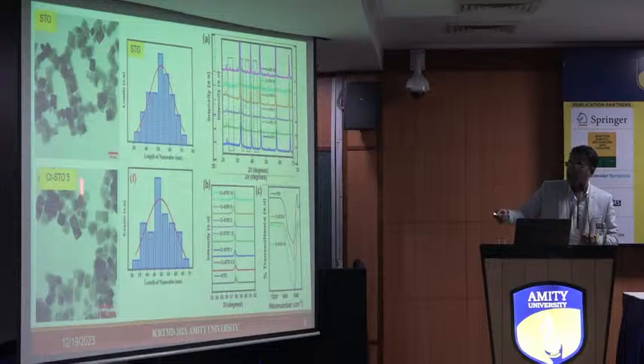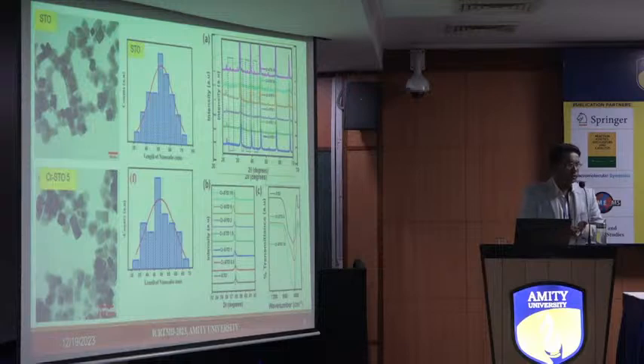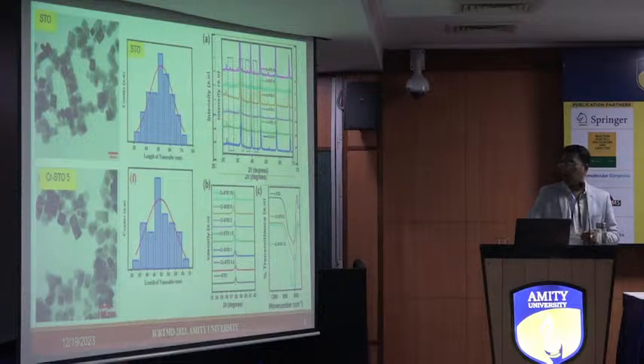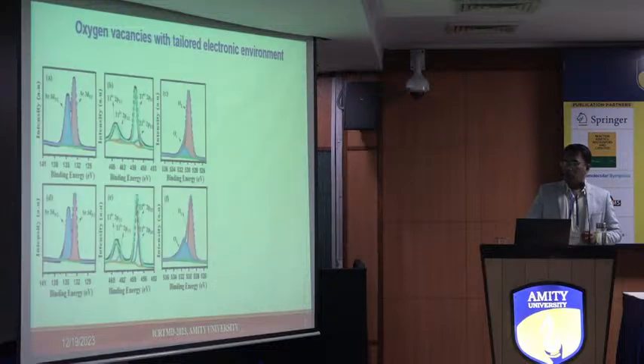And so if you look at the size distribution curves, you will notice that there is hardly any change in the size. So size is not playing a role, that we confirm. Second, phase separation is not playing a role. So whatever the effect is, it's because of the doping. Oxygen vacancies we quantified using XPS. You can see this is without doping, this is with doping. The oxygen vacancies are increasing.